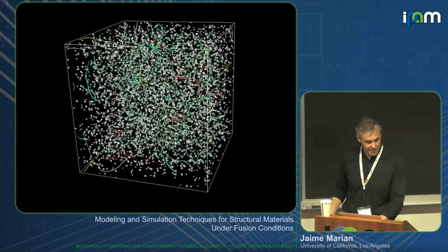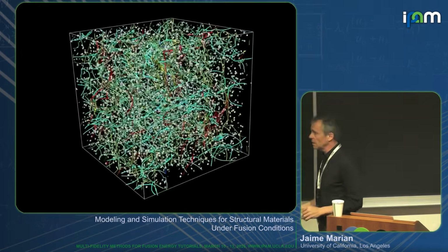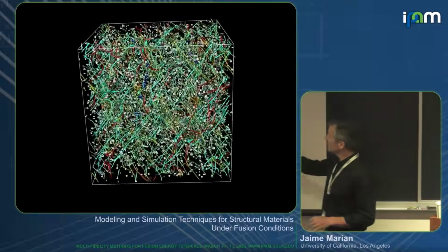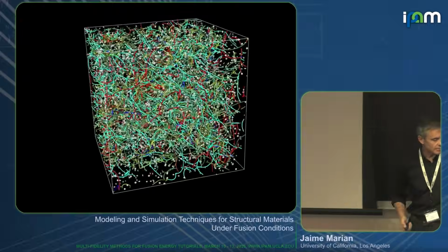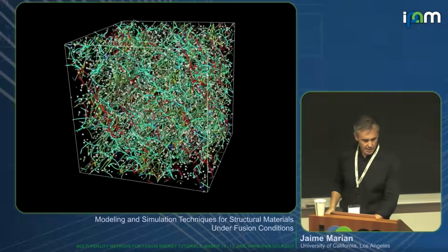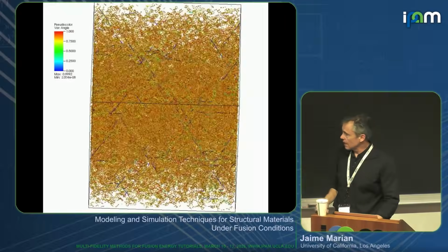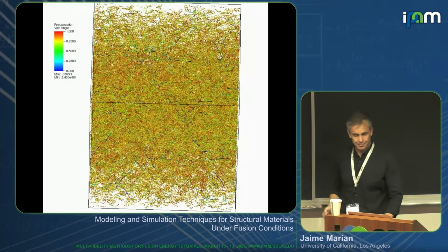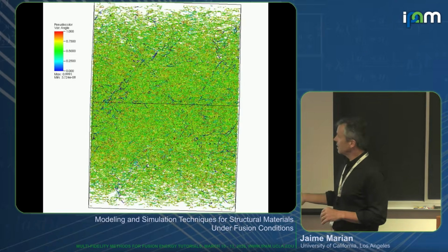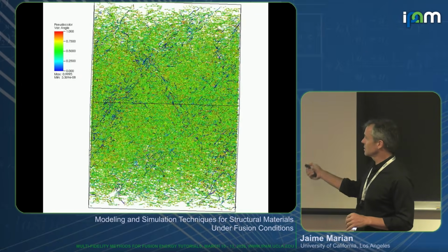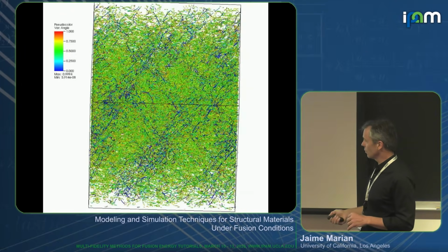And then we can elevate this into large-scale simulations with many of these defects and many dislocations, and then we can see what the effect is. Okay? And if you filter simulations like that through another algorithm, you'll see that these dislocations form channels. Eventually, they will form channels.